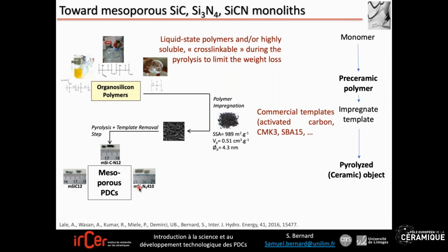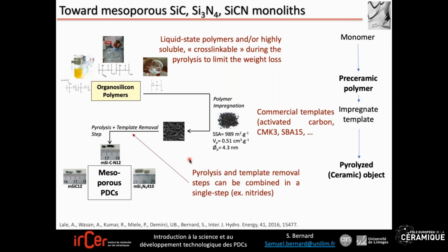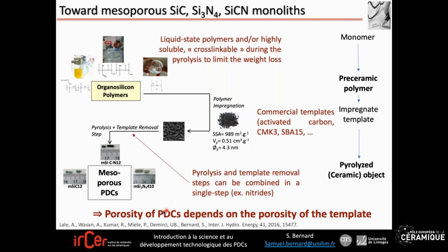Okay, so in fact, you can use different types of porosity, starting from mesoporous to macroporous porosity, and you can also form PDCs with a hierarchical porosity. And in fact, the porosity of your PDCs closely depends on the porosity of the template you use. If you use activated carbon as monolith, you form PDCs as monolith, which are mesoporous. So such materials can be used as catalyst support.